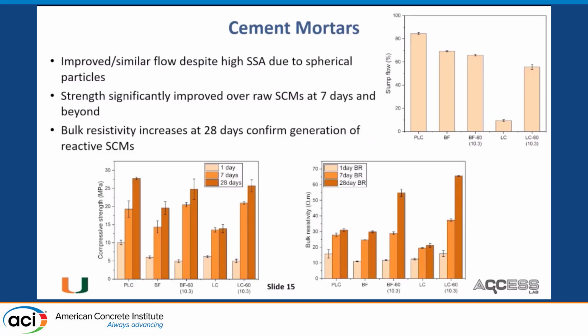Now, we actually looked at cement mortars as well, and this is a work in progress, but we see, for example, improvement in workability. We don't actually see a huge loss after mechanochemical activation in the slump flow, like one would expect with calcined materials. In the basaltic fines, the workability is only slightly reduced, and this is interesting because the specific surface area has actually increased greatly. So presumably there's a competing effect of the spherical particles being generated, which are kind of compensating.